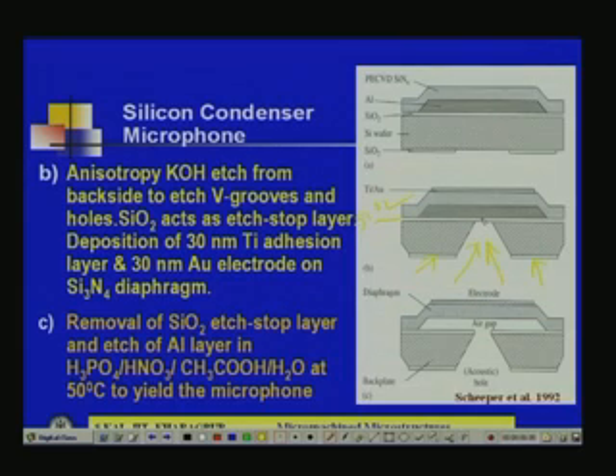After that, this silicon dioxide etch stop layer has been removed, and then this aluminum is etched. The aluminum etching solution is phosphoric acid H3PO4, HNO3, acetic acid and water at 50 degree centigrade. Before aluminum etching you just have the gold film, and before gold a small amount of titanium has been deposited for proper adhesion of the gold with the PECVD nitride. This is PECVD nitride, this is Si3N4, this one.